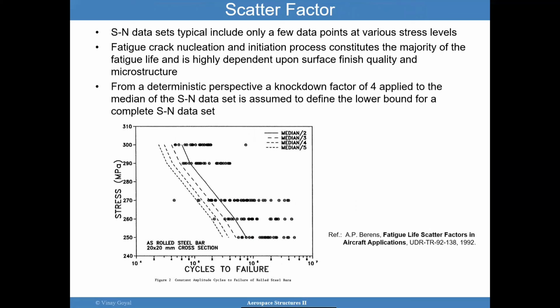Typical data for scatter factor. There's a lot of scatter in this kind of testing. SN data usually include only a few data points at various stress levels. Fatigue crack nucleation constitutes the majority of the fatigue life and is highly dependent upon the surface finish and quality. I told you that those samples are tested very carefully, but you do get a significant amount of scatter in the data. And you can see here, if I take the median and divide it by 4, I start to envelope more and more of that SN diagram, this SN data here.